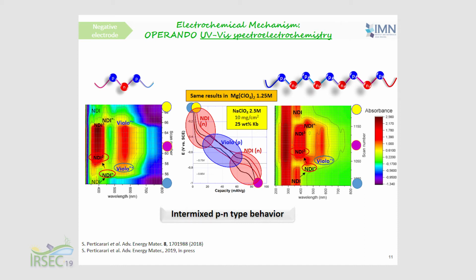We have done some operando characterization of what happens during one full charge, discharge cycle, to know the reaction mechanism. And here I show you some results of operando UV visible spectroelectrochemistry. This technique allows to detect which species occur at which voltage. So I will only summarize shortly. What we find is that at the beginning of the reduction, we reduce the NDI part, then we reduce the viologen part, and at the end, we put a second electron on the NDI part. So we call that an intermixed N and P-type behavior.